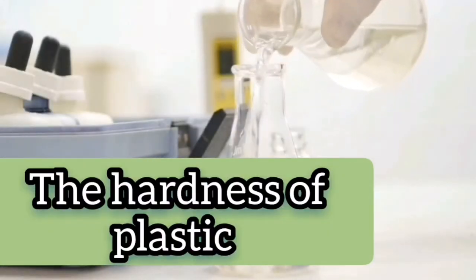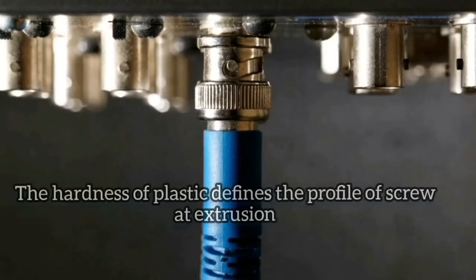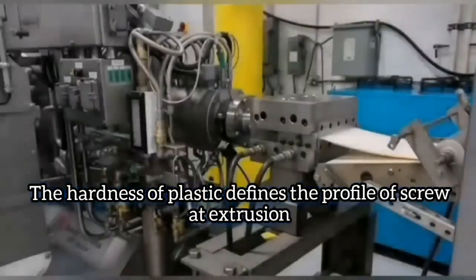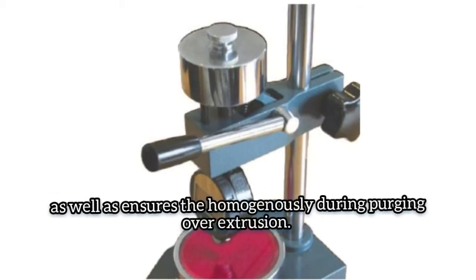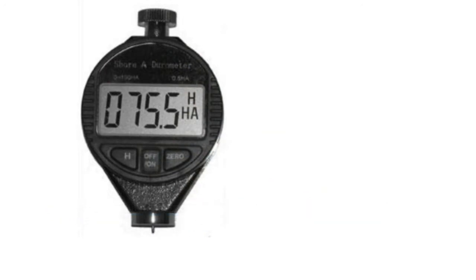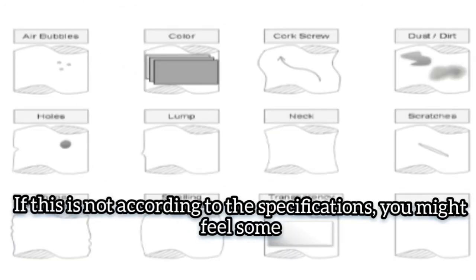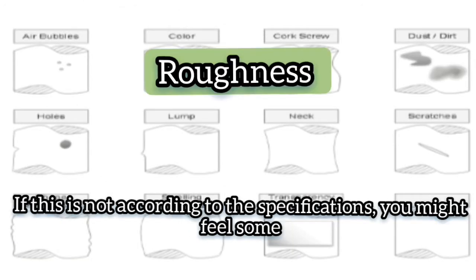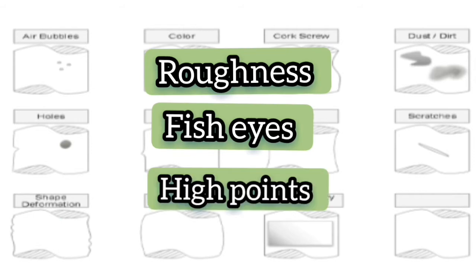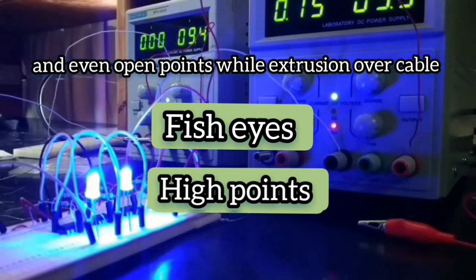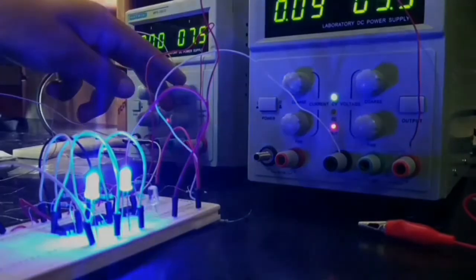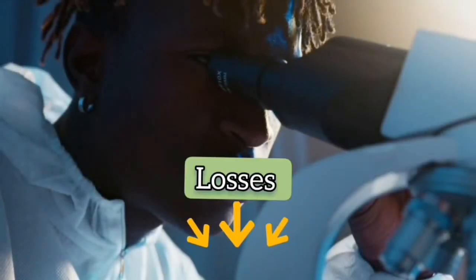The hardness of plastic: the hardness of plastic defines the profile of screw at extrusion as well as ensures homogeneity during purging over extrusion. If this is not according to specifications, you might feel some roughness, fish eyes, high points, and even open points while extrusion over cable and might consequently have to stop the machine resulting in downtime and losses.